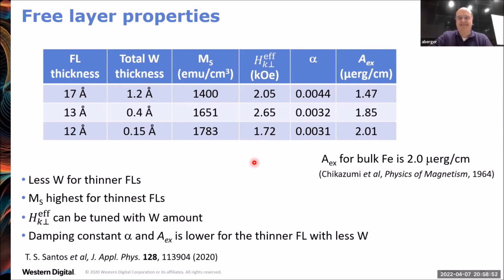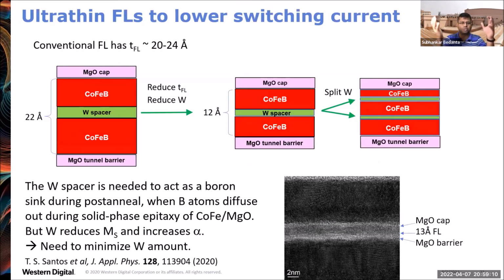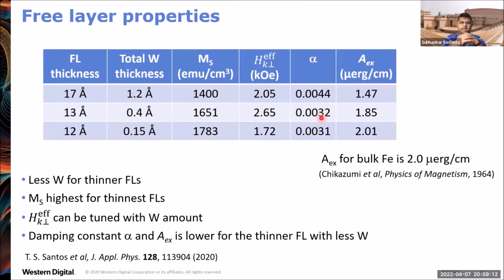Actually, I have a question similar to what Andreas asked, but he has already asked and you have clarified. I just wonder what happens when you put tungsten on or in between cobalt, iron, boron, that the alpha value also decreases. In this slide, you show 0.004, it goes to 0.003, which is definitely better. Because when you put tungsten, there may be some spin pumping happening, and that should rather enhance alpha.